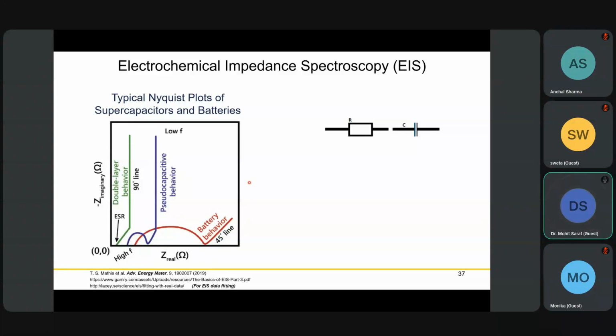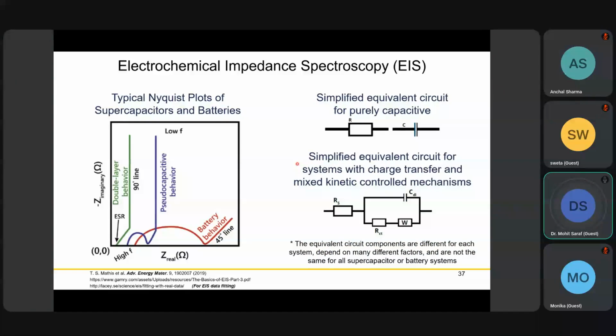It also tells you a lot about charge transfer resistance, solution resistance, and Warburg resistance. When we get the data, we study it using an equivalent circuit, checking which kind of resistance the system might have and which capacitor components are there. We make different equivalent circuits, analyze them, and determine which component is causing which resistance.